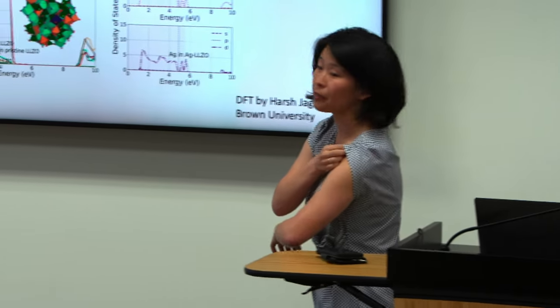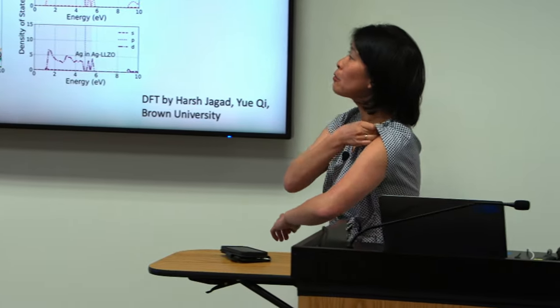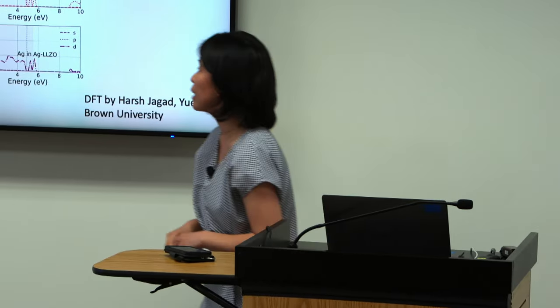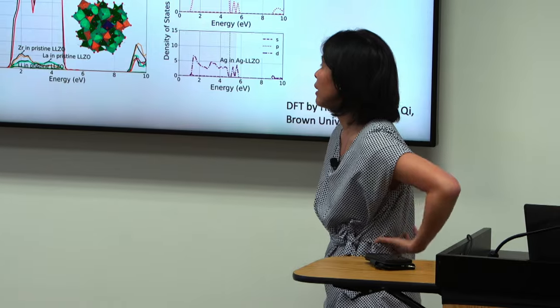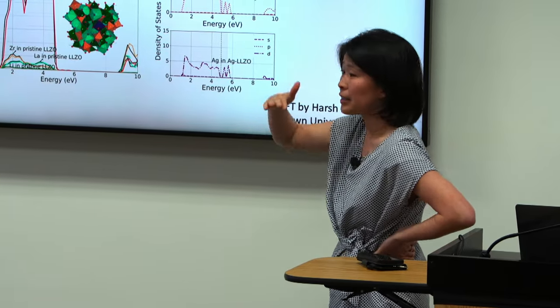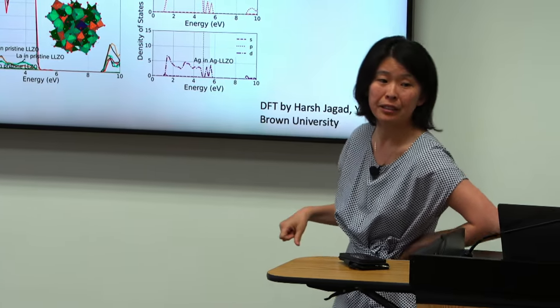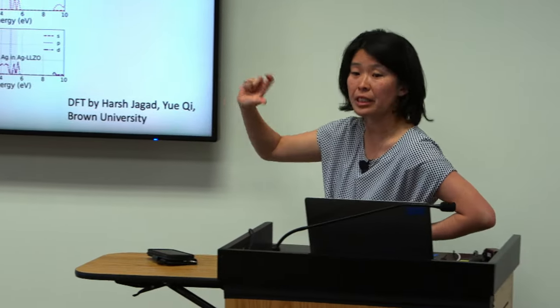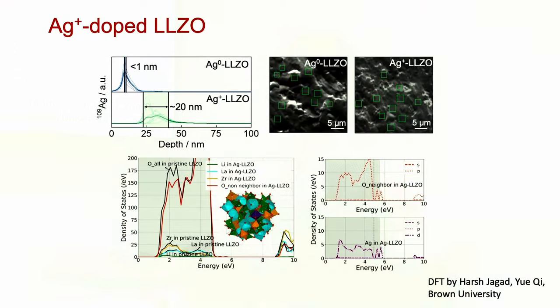And of course, the question is, why does this work? Well, it looks like after a great deal of chemical analysis and also working with simulation experts, that the silver is entering into the LLZO structure. It looks like it's exchanging with the lithium there. We don't have a direct measure of compressive stress at this location, but it would indicate that there is some compressive stress right at that surface layer, and that's preventing the formation of surface cracks that propagate deeper in the material and lead to failure of the overall structure.